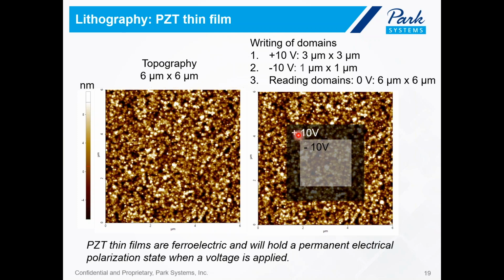And then we will choose a smaller region, in this case a smaller 1 micron by 1 micron region, and we will put it in the center of the original 3 by 3 micron scan, and then we will apply a negative 10 volt DC bias to the tip for this 1 by 1 micron scan, and we scan it. So this is the writing procedure.